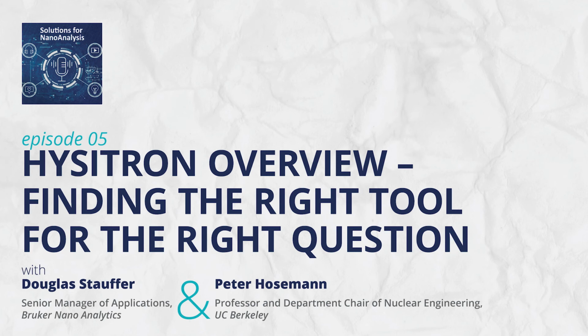What is hardness, right? What does hardness mean outside of the resistance of a material against penetration of another object? It's very hard to relate hardness to an engineering property. We engineer materials with yield strength and strain numbers and UTS and fracture toughness, not with hardness, unless you're a hard film coating person. So while it's very useful to get large numbers of data quickly, many times we use hardness much more as a qualitative assessment. We then have empirical equations to relate towards maybe a quantitative design number. But hardness by itself is interesting, but not something we use to design a reactor with directly.